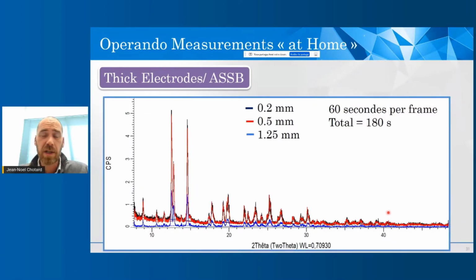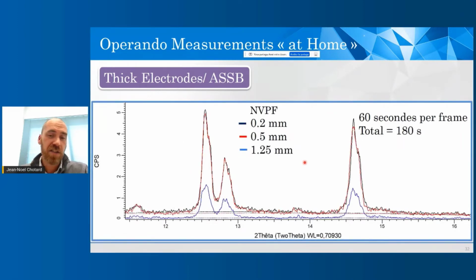We first tried to measure different pellets of different thicknesses, and you have here in black a pellet of 200 micrometer, in red 500 micrometer, and finally in blue 1.25 millimeter thick electrodes. And those measurements were done using 3 snapshots, so that's 60 seconds per snapshot, which is pretty fast too. So obviously, the thicker the electrode, the more it will absorb. But still, we are really able to have pretty nice diffraction patterns within a very, very short time.